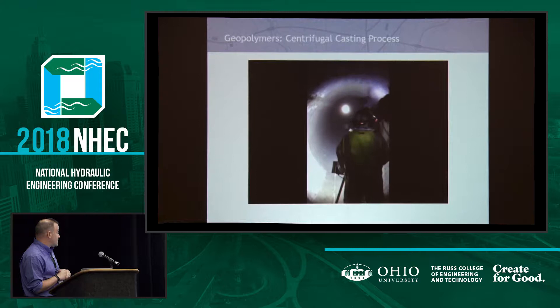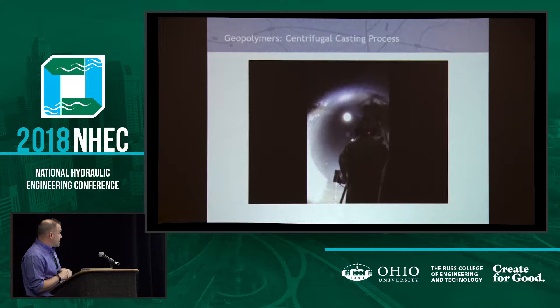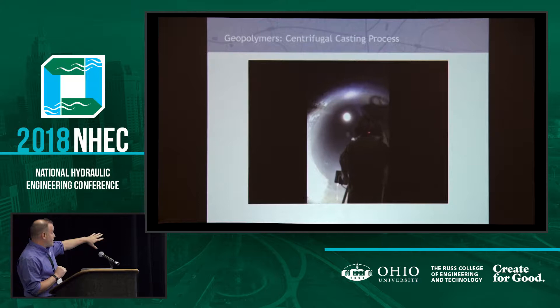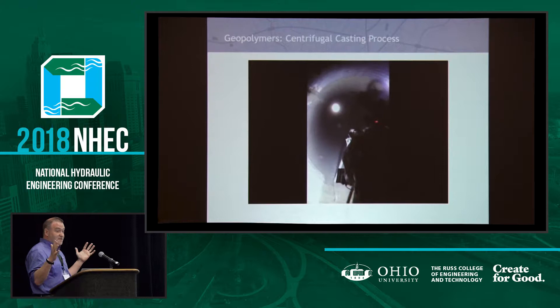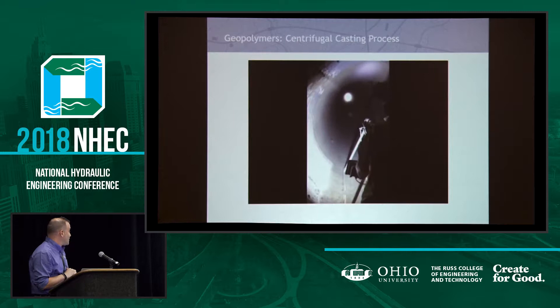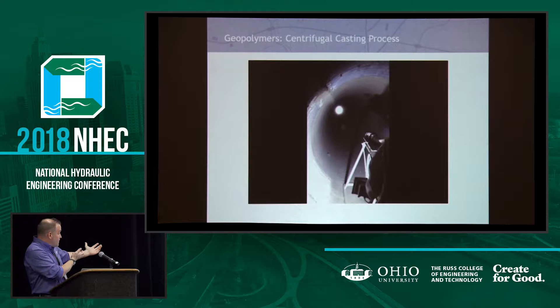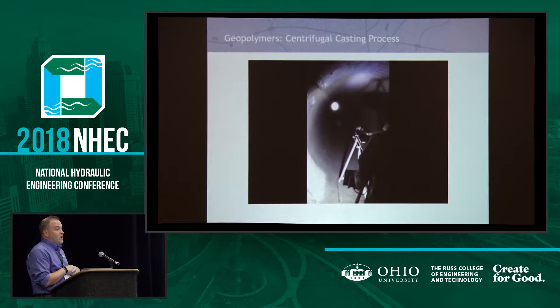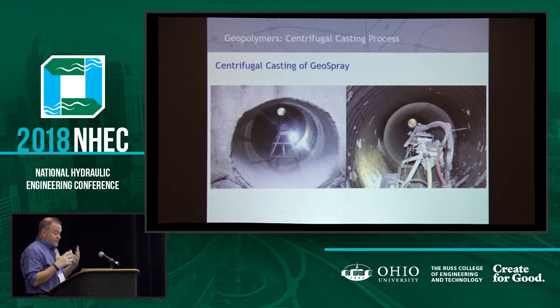This is an actual job on State Road 446 in October of 2015 in Indiana. The portion that looks a little more brown has had a single pass applied to it, and everywhere else hasn't been applied yet. They're applying about a half an inch on this pass. I think this pipe was like 350 feet long, and they ended up putting an inch and a half on it. It's been in the ground three years and it looks a lot better than some of those pictures I've seen, because I walked through it last December. They have a spin head that's moving back and forth. It's really slow — it's moving through the pipe at probably about 12 inches a minute, so they're talking about an eight-hour process to do a half inch on that pipe.